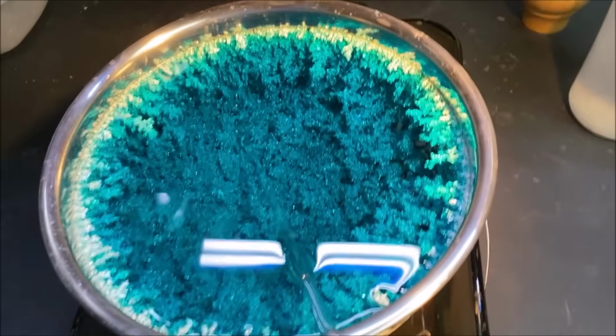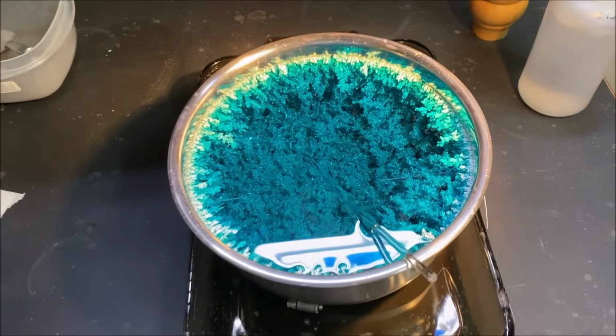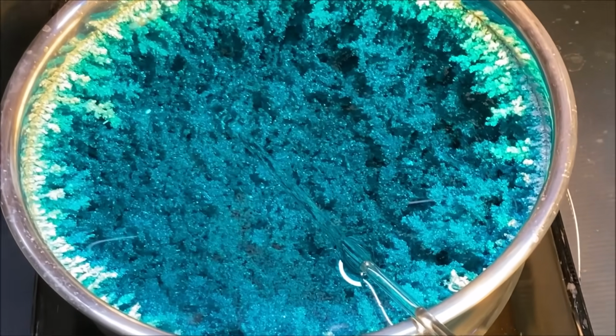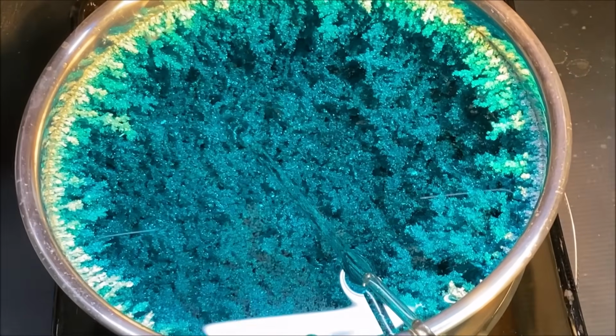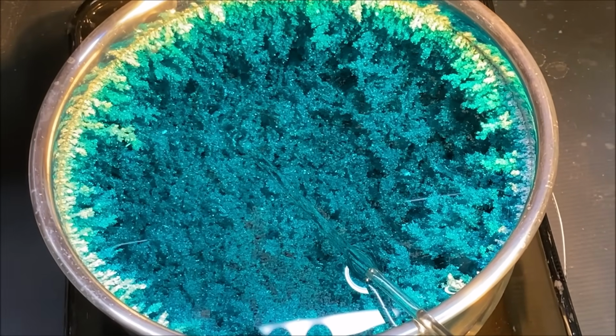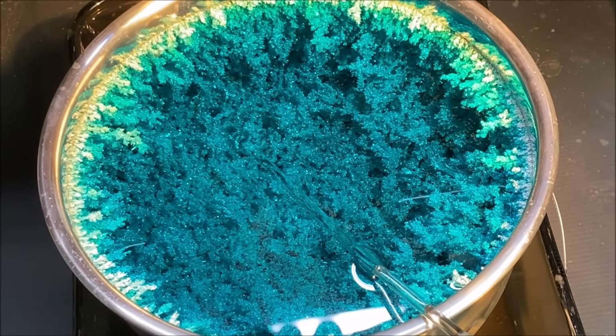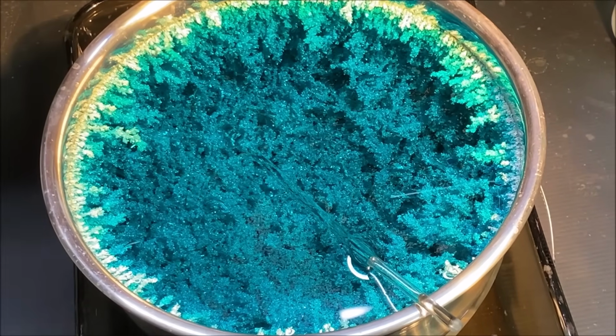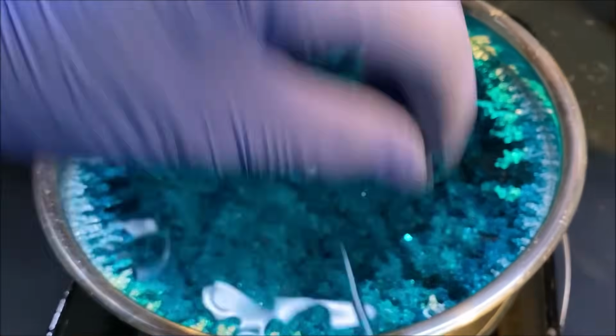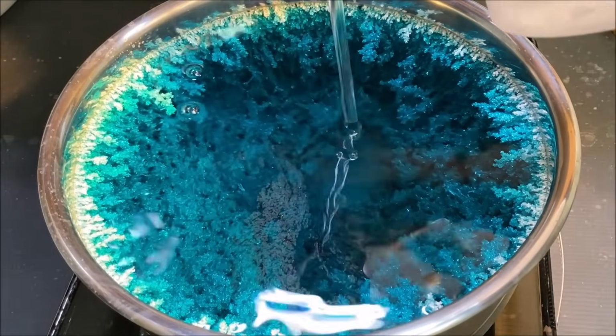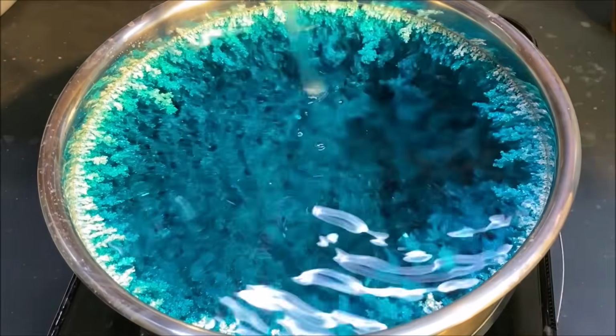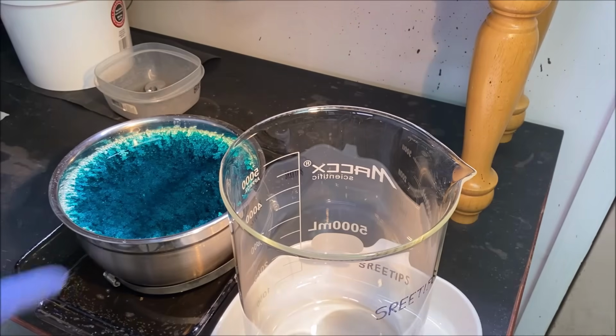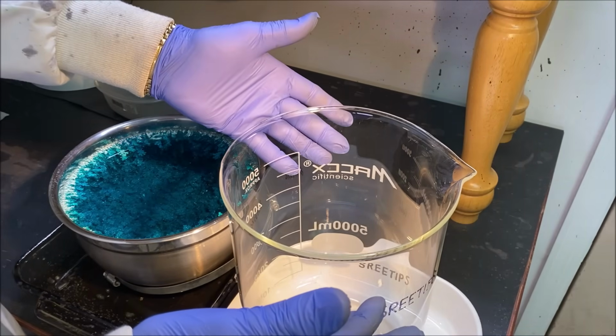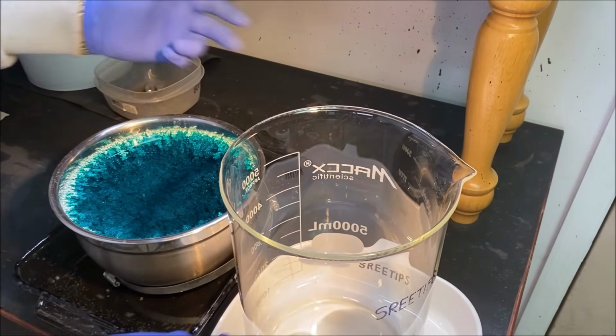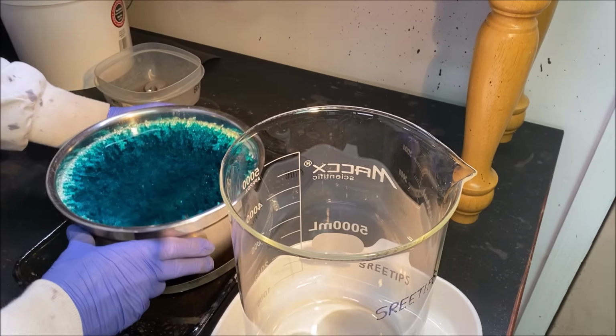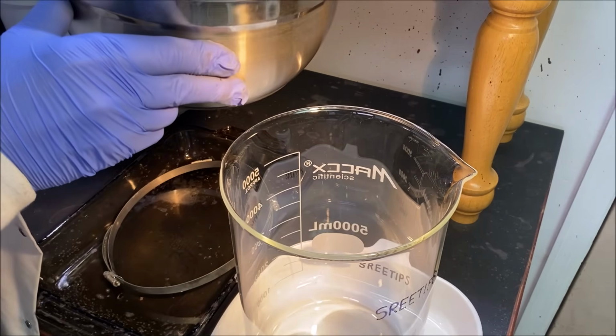This is the pure silver crystal that we've grown over the last 2 weeks. Should be about 2 kilos of pure silver in that silver cell. Let's get this thing out of the way here. Just gonna lift the cell up now and empty the used electrolyte into this beaker. Try to do this without making a mess.